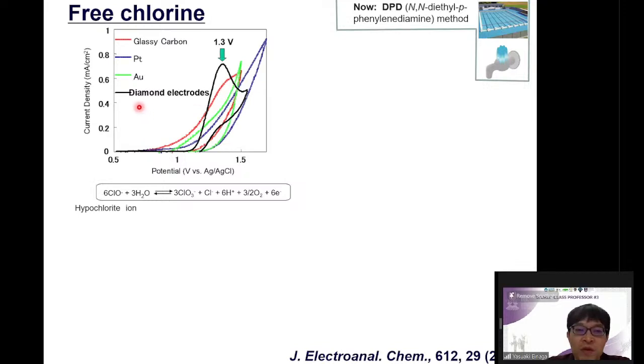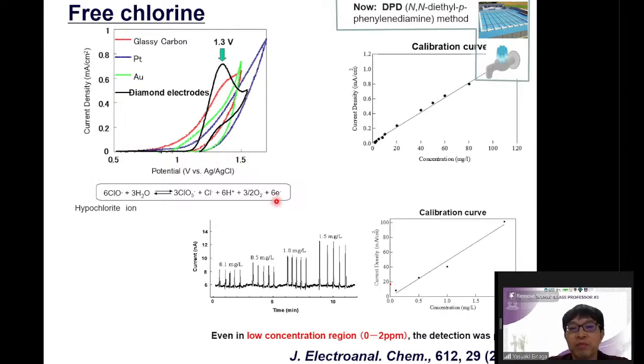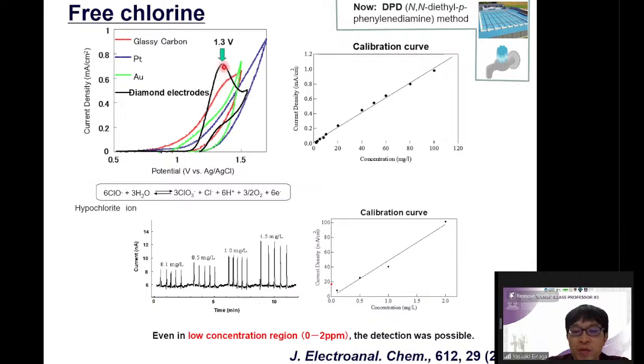On the other hand, when our diamond electrode is used, a clear oxidation peak is observed and no oxygen evolution is observed. So it means this signal reflects the concentration of chlorine directly, and the sensitivity is very high. This is due to the advantage of boron-doped diamond, the wide potential window and the low background current. Okay. So then we could observe the calibration curve depending on the concentration.